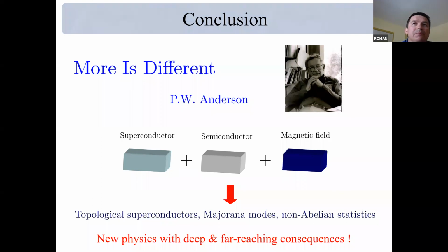Yeah, so the way to rule out trivial bound states, our way, was to simulate different scenarios. And in the paper, we simulated different scenarios that came to mind. So what are the suspects that we considered? We considered a gapless phase, and we considered some finite system with a gapless phase. So there's some splitting which is finite, and we considered some localized end states residing, say, at one end of the system.